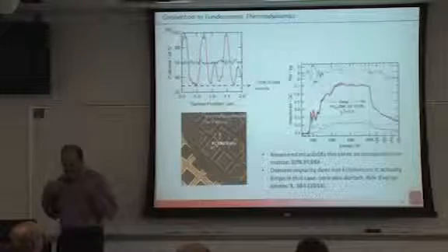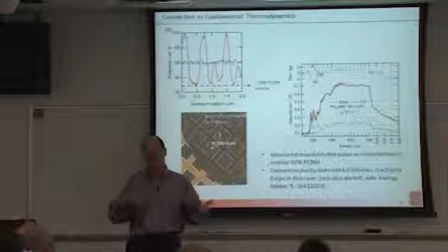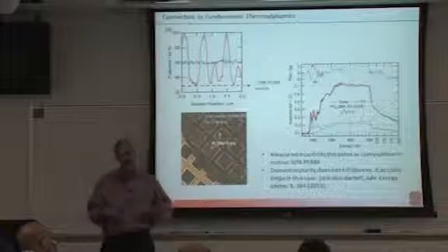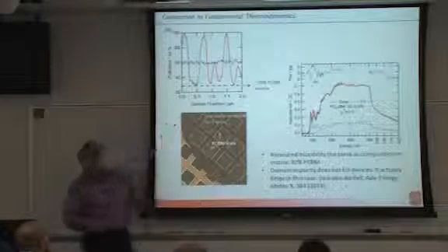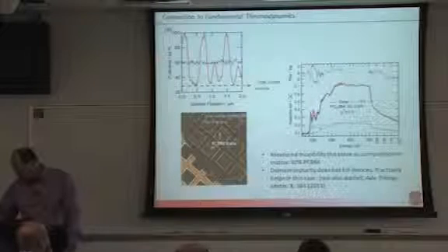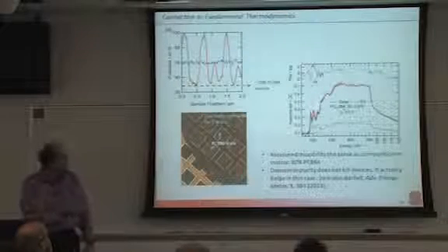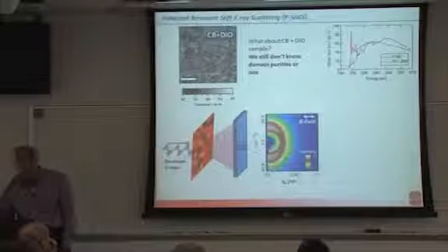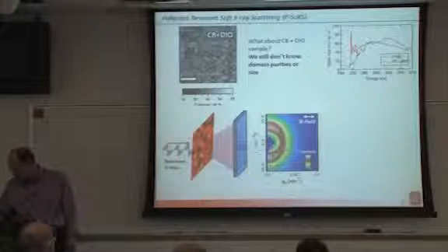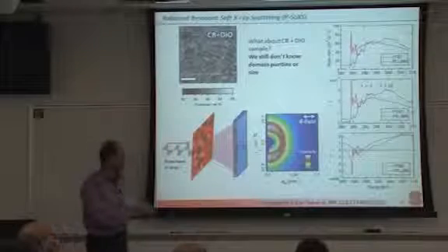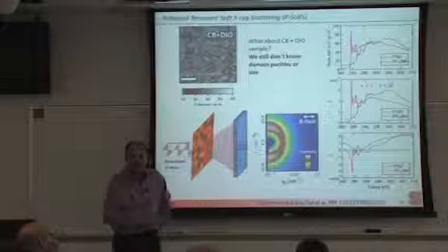here. So I think it would be hard to imagine that I can have a non-equilibrium process like spin casting that would actually give me purer domains than what this miscibility limit is. And so in this situation, you actually reach these thermodynamic limits. I think we're close to that. All right. So we're still having problems, though, to understand what happens with the DIO. So now we do scattering. And there, I didn't allude to that completely, I have a real part, but also an imaginary part.